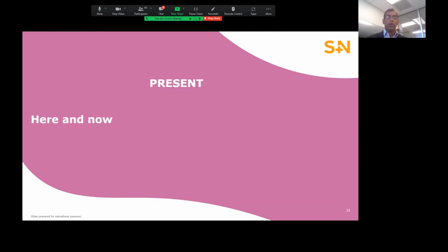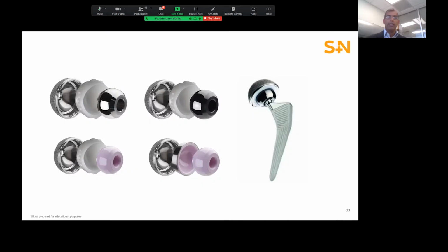So this brings us to where we are today. And this slide displays the bearing combinations most commonly used in modern hip arthroplasty. These devices consist of a highly cross-linked UHMWPE liner locked into a titanium alloy shell. That alloy is typically titanium 6 aluminum 4 vanadium, or Ti6-4. The liner is then paired with either a cobalt chrome, ceramic or oxidized zirconium femoral head.